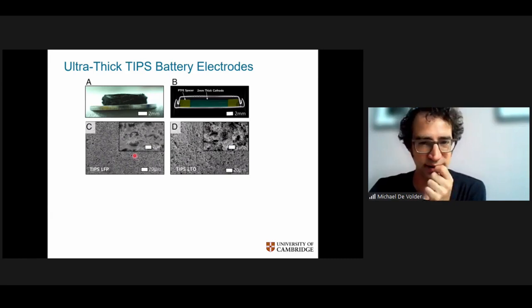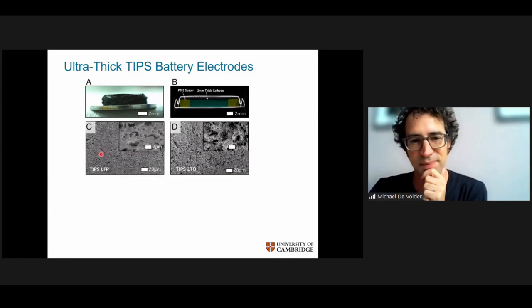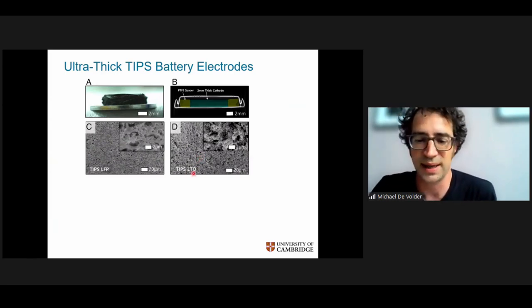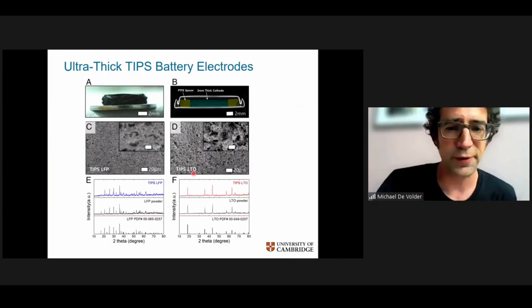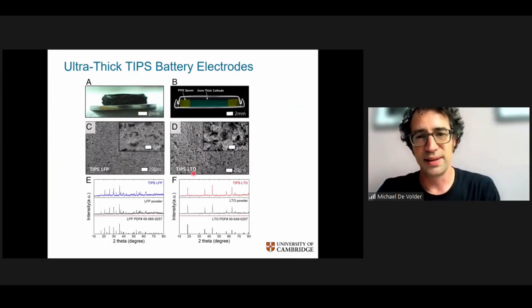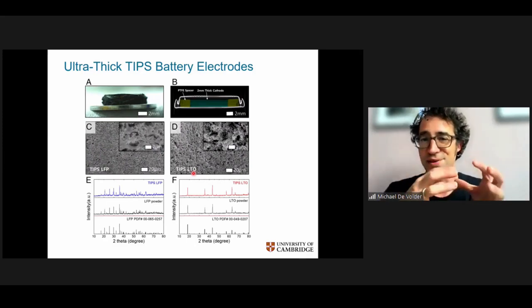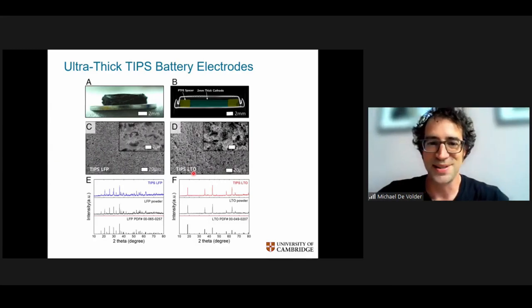And so you can see here on the left-hand side an example of the TIPS process being used for making a thick cathode material. So LFP stands for lithium iron phosphate, is a typical cathode material. And on the right-hand side, we've done the same for anode material using LTO, that's lithium titanate. And so the first thing we did is we checked whether this phase segregation process damages our battery materials, the little houses in which we put the lithium ions at all.